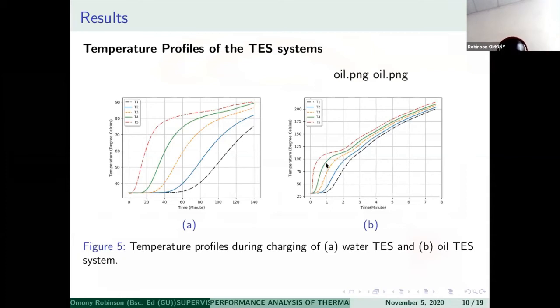However, oil having high storage density, we can charge it up to a temperature of around 200. Meanwhile, water, we were able to only charge to around 89 because bubbles started developing in the storage, and this stopped the increase in temperature. But for oil, we were able to reach a temperature of 215, and we stopped there.